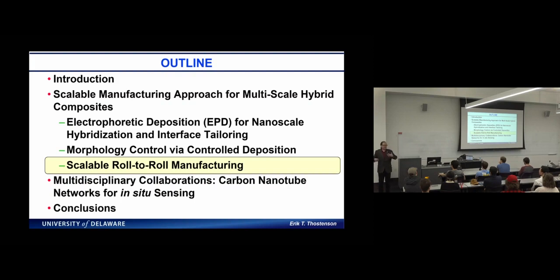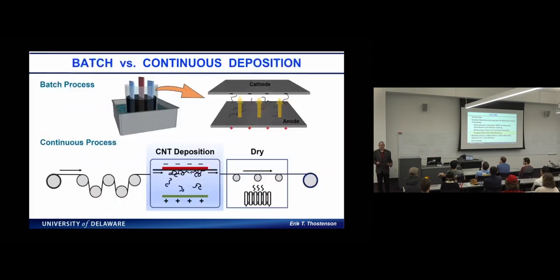But we've now had this capability where we can scale it up as a roll-to-roll process. So this is, again, a batch process versus a continuous process. Here we have our fibers. They can go through a deposition bath. We've developed a small pilot line in my lab, and it's partly because there's so much interest in the sensing work, everybody wants some of the material. So I get calls from companies asking for it, and I'm like, well, we can make a couple square inches for you, but they want yards. So we developed this pilot line.